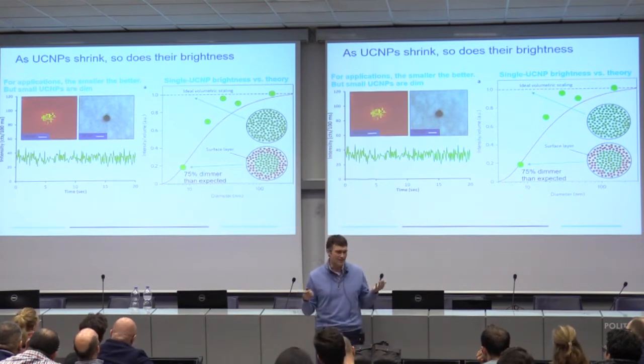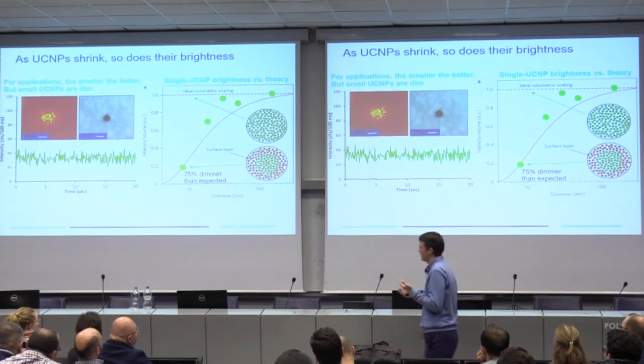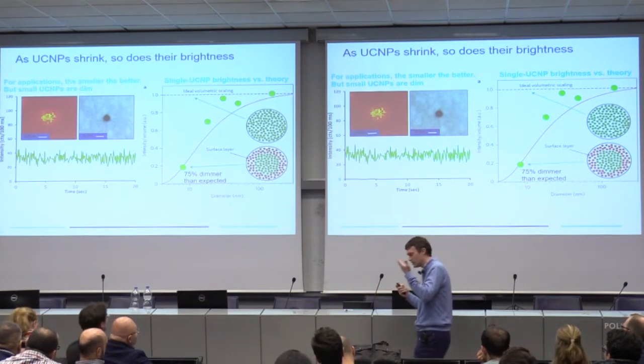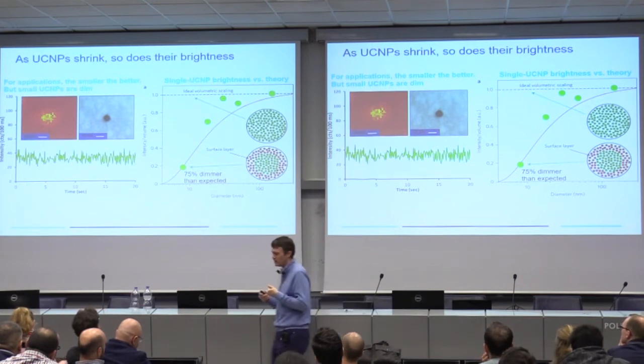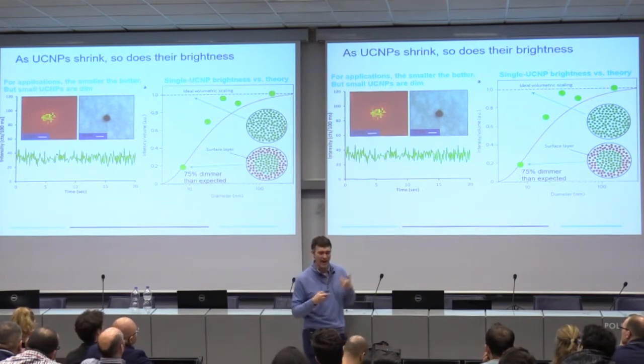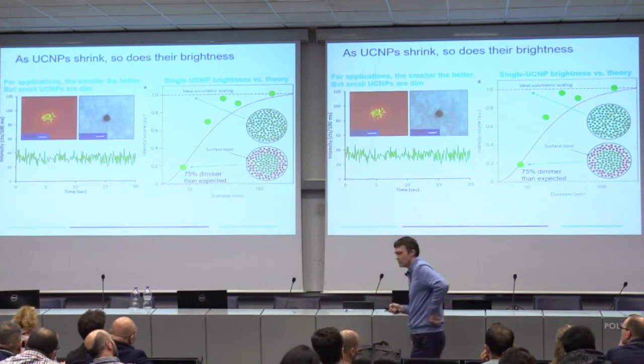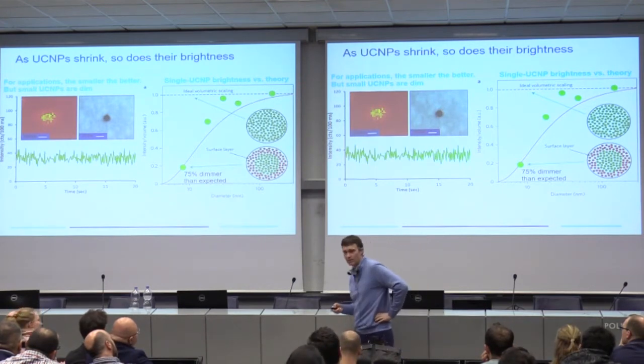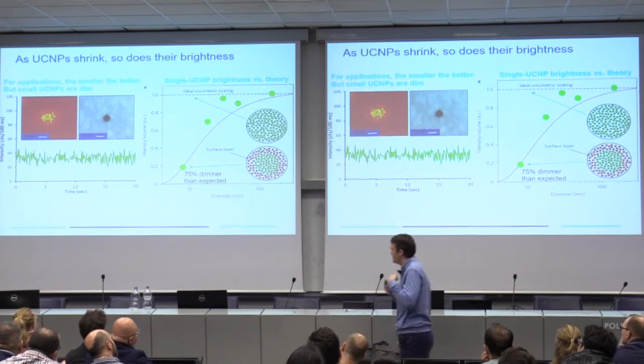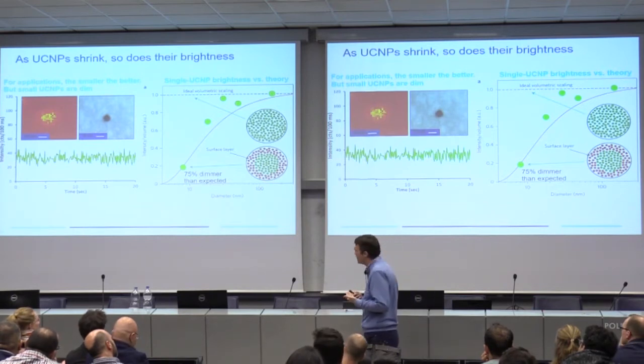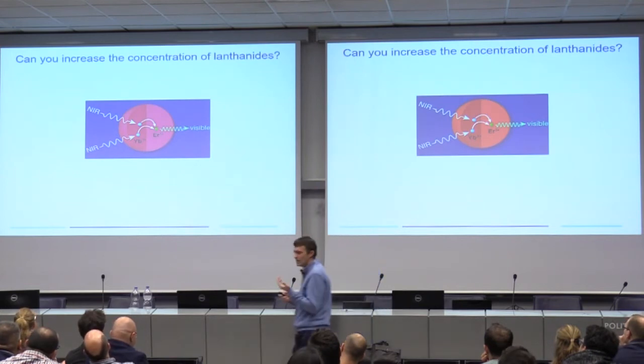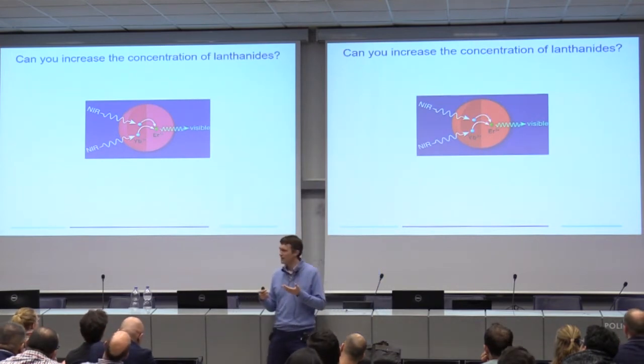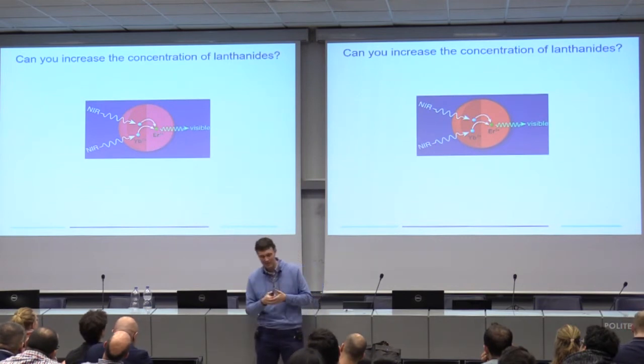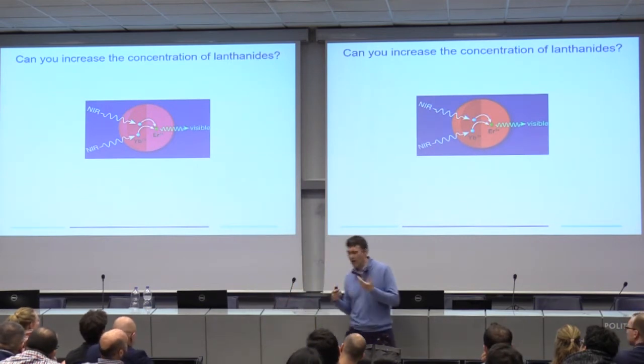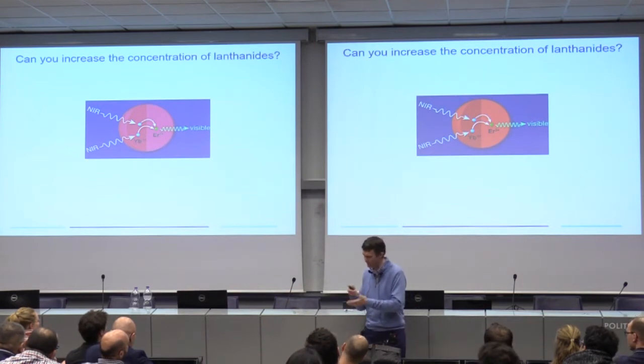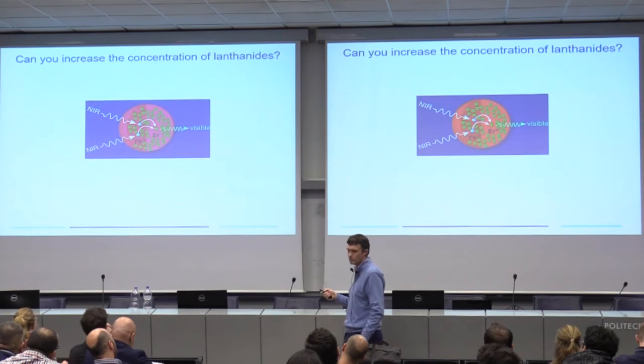And the reason for that, for anyone that's dealt with materials, is you know that ultimately surfaces start to matter. At the surfaces of these materials, you get a lot of non-radiative recombination. So surfaces turn out to be bad and give you sort of a dead layer in these materials. And so even though we could make small sub-10 nanometer particles, we couldn't really see them. This got us asking, well, how do we make them better, right? The first thing that you think of is, well, can you just put more emitters inside the particle? As I'll mention in a second, there's sort of a canonical composition, but can you just stuff more material into these particles and try to make them brighter that way?